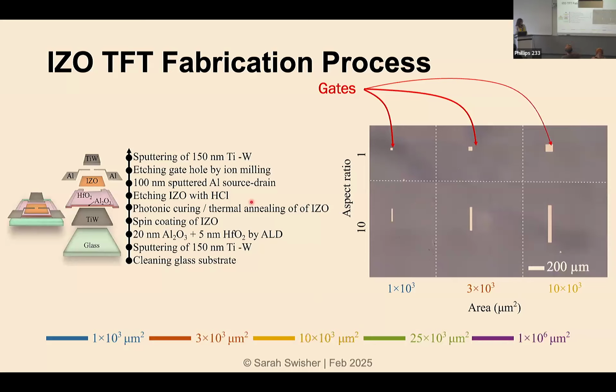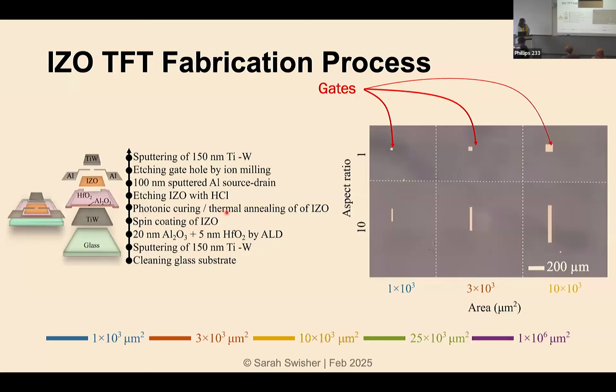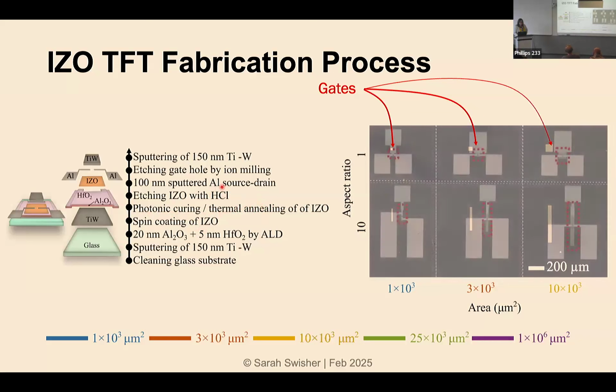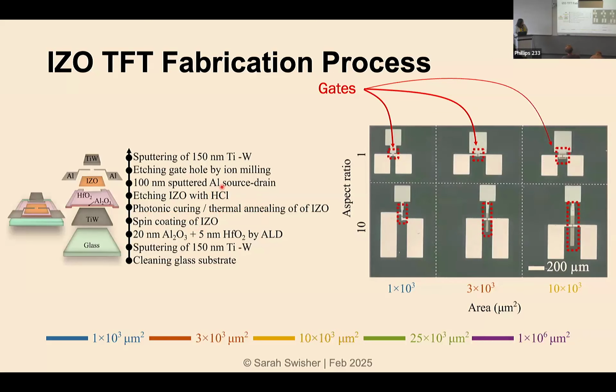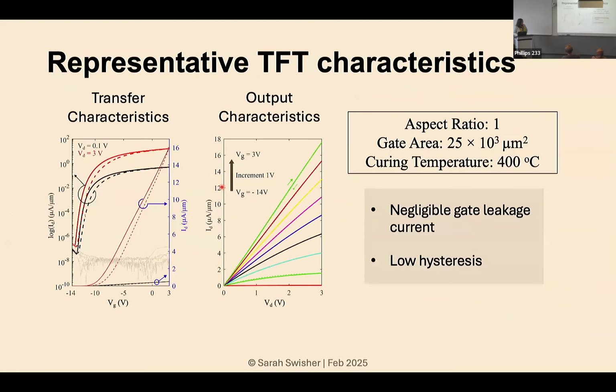And again, remember that we're not looking at the size of the transistor itself, the channel dimensions are not varying here, right? The size of the gate is just determining the temperature, and therefore it's determining how the material is cured. So these are fabricated with a titanium-tungsten gate, a bilayer high-K gate dielectric of aluminum oxide and hafnium oxide. We then spin coat our indium zinc oxide sol gel, and we did photonic curing and then the thermal annealing as our control. We etch and deposit our aluminum source drain as a top contact with titanium-tungsten. So this is what some of those devices actually look like, and we're trying to highlight where the gates are and where the semiconductor is going to be.